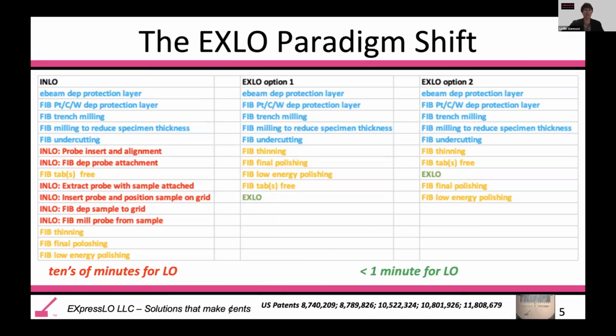Many people might be familiar with the so-called in situ lift out technique. With in situ lift out, there is a probe that is mounted either inside of a FIB or on the chamber wall of a FIB. This requires that the probe be inserted and somehow attached to the specimen, or using grippers grabbing the specimen. It also requires the sample to be attached to a suitable grid, and then the probe itself to be removed from the sample. And these are all the steps in red.